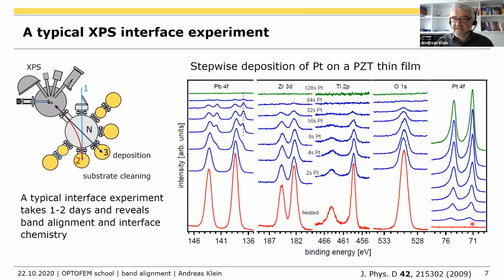Now you deposit platinum on top and you see how the platinum is getting more and more, and the oxygen, titanium, zirconium, and the lead disappear. You see that already with the deposition of the platinum, the lead peak is split into 2 components. The one which arises here is a metallic lead peak. And that is because the platinum itself is reducing the oxide. That's something which will come later.